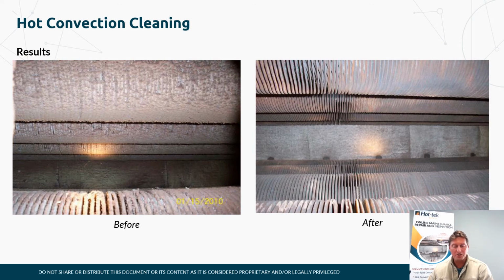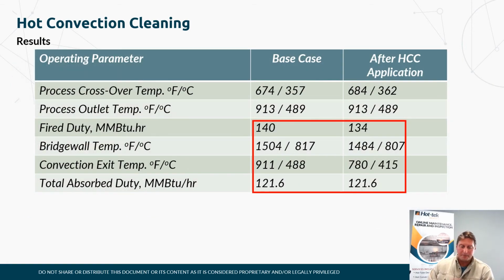So this is before and after. Again, no damage to either the fins or the ceramic fiber in the lining of the convection section. Moving into the case study, the firing duty, as you can see, decreases by 6 MMBTUs per hour, while our absorbed duty remains the same. So we're getting a much more efficient convection section after the cleaning. Payback was under 6 months, and again, this case study included both access door creation and convection cleaning.